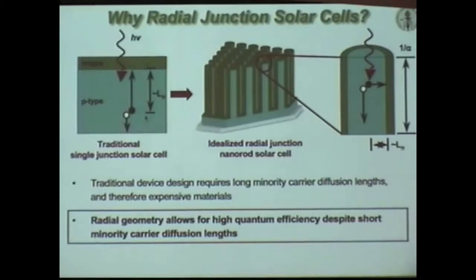This radial geometry would in principle allow for a high quantum collection efficiency even for really cheap materials, or non-stoichiometric materials, or materials you would be crazy to use in this planar design, that we are now making solar systems out of in our lab. One example is rust, where you need a few microns to absorb the light, but it's highly non-stoichiometric, as hematite found in nature is highly defective, and carriers can only move 40 nanometers. So only the 40 nanometer top part is live, and the other 3 microns is just dead. So we just make 3 micron long, 40 nanometer diameter rods, and they're alive. Make them out of pyrite, fool's gold. So we're making combinations of solar active materials out of fool's gold and rust. You can decide whether we're crazy.